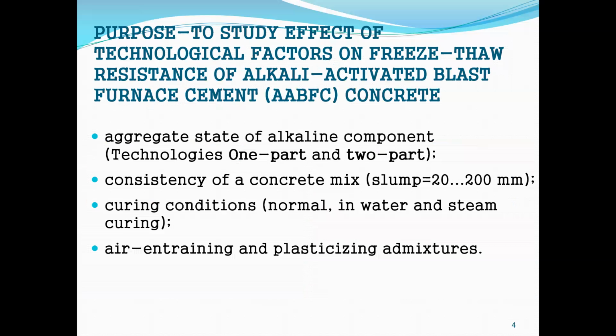The peculiarities of porous structure cause advanced freeze-thaw resistance of alkali-activated blast furnace cement concrete. Porous structure of such concrete in one's turn is caused by technological factors such as consistency of fresh concrete, aggregate state of alkaline component, curing condition, and application of chemical admixtures. The modern requirements to consistency of fresh concretes are governed by practice. Production of alkali-activated blast furnace cements, namely under all-in-one technology, causes the expediency of alkaline component exactly in dry form.